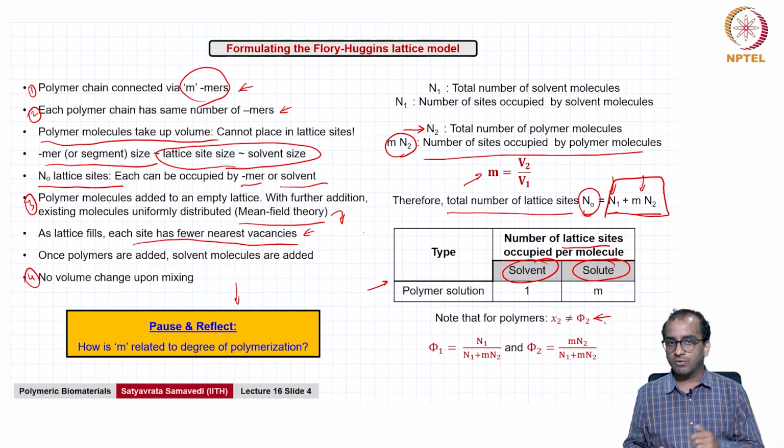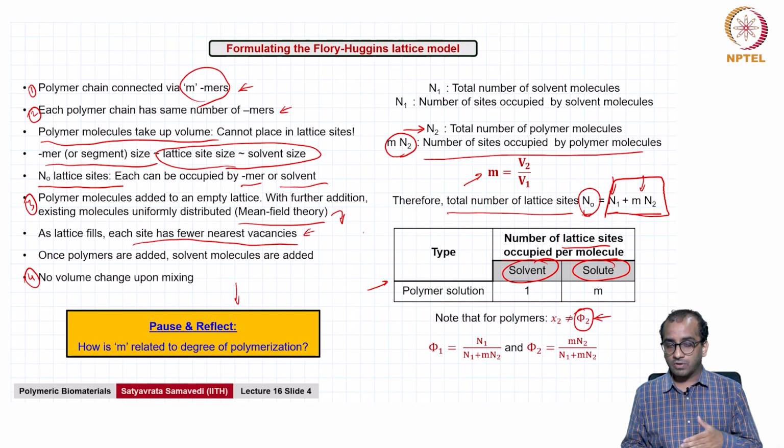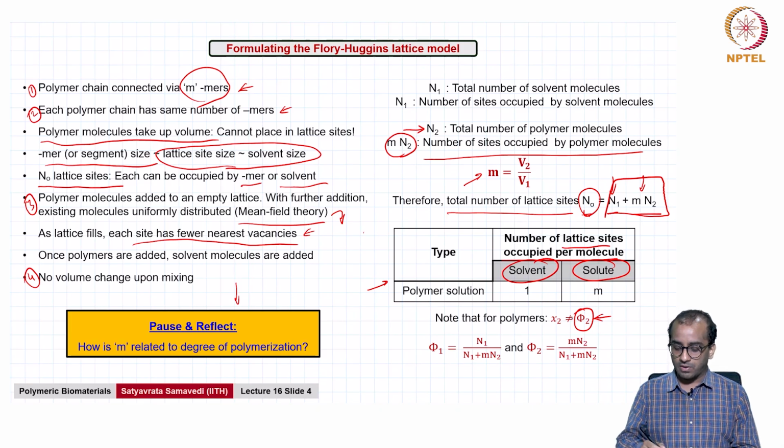For small molecules they are the same. For polymers we are now switching to volume fractions, phi, one because of the size, and two, for us to know mole fractions for polymers you have to know the exact molar mass and molar mass distributions, whereas volume fraction can be easily obtained if you have mass and density. So, it makes our life easier to deal with volume fractions for polymers rather than mole fractions.